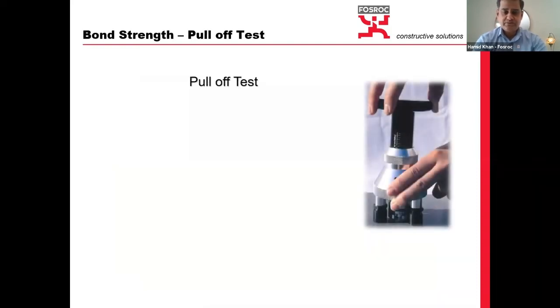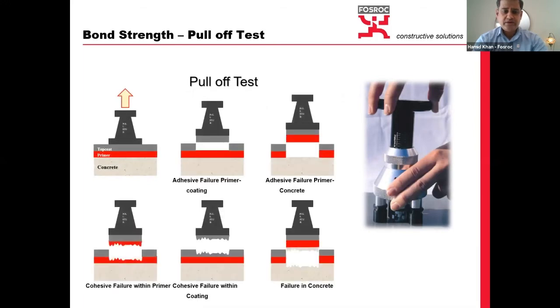The site bond strength is a bit different. So these are the different pull-off tests, basically for coatings, but we can consider the same thing. If there is a failure between the primer and the repair mortar, it is called adhesive failure between primer and repair. If the failure is between the primer and the substrate, this is called adhesive failure between the primer and concrete. If the failure is within the primer, it's a cohesive failure. If the failure is within the repair mortar, I'm taking coating as mortar here because this is a repair webinar, it is called cohesive failure. If it's a failure in the concrete, this is called failure in concrete, which is quite desirable for us in order to have a good repair mortar.